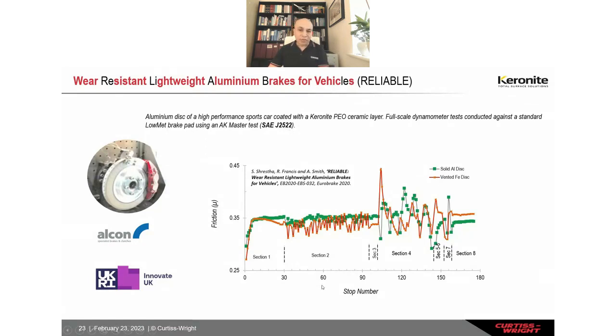The test was done to the industry standard SAE J2522. As you can see, there are a lot of tests going on here, from harsh braking to a lot of snubs over these eight sections of hundreds of stops. What this graph is showing is that the red is the vented, typical conventional grey cast iron, and the green one is the ceramic PEO coated aluminium. In fact, the coated disc shows even less scatter, and a friction coefficient very similar to the existing material, which gives us a lot of confidence for use of this material in such applications.